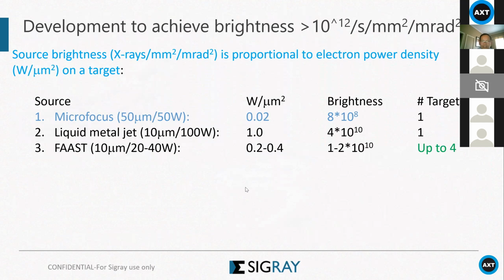Clearly, you can see that our source in that number is not as bright as a liquid metal, but the liquid metal only has one target material. So as I have shown before, you can get orders of magnitude more fluorescent signal by selecting the proper X-ray energy. So we can have 4 target materials in the same X-ray source. You can easily switch. That more than offsets it. We have a superior gain over the single target with liquid metal.